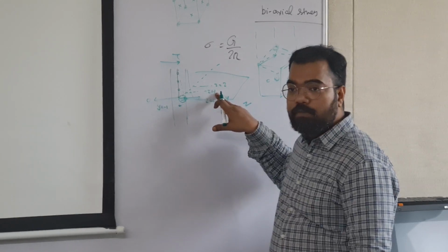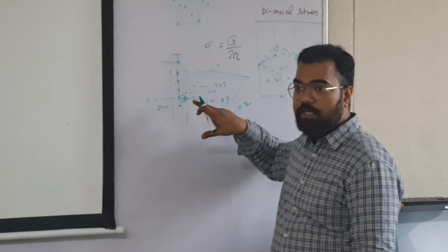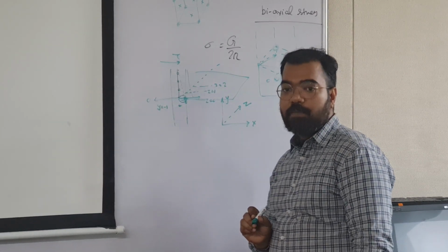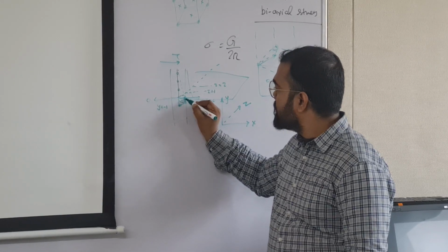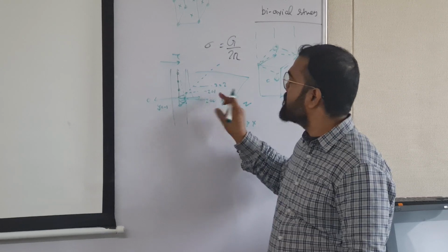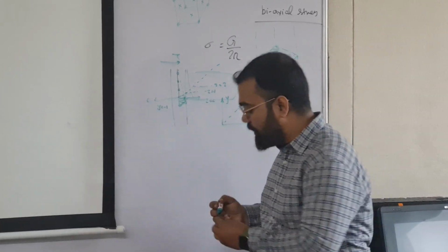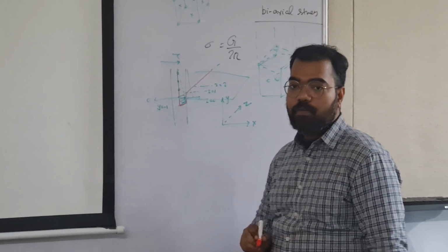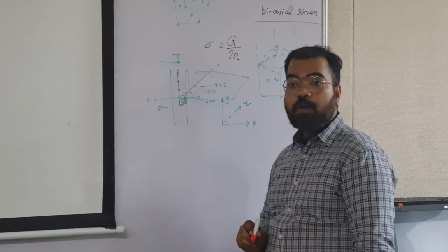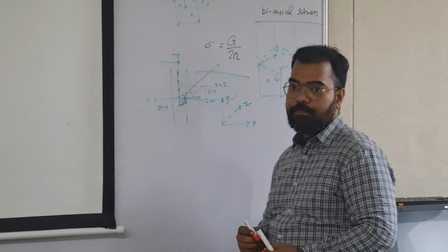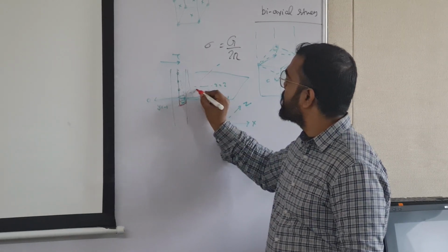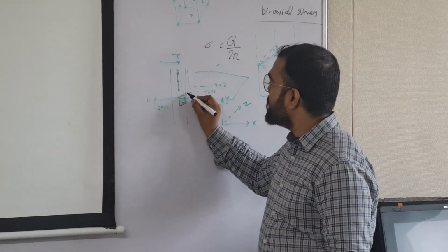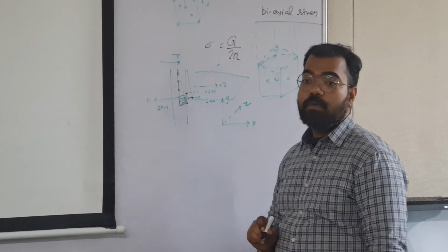But what happens to z is equal to 1? It is not there. It is at y is equal to 0, right? So I could put one atom there also, but then I don't put any other atom. Then what happens? The dislocation extra half plane definition is this for z is equal to 0 and z is equal to 1. And beyond that, now if I want to draw the dislocation line, then that dislocation line will look like this. Right? Now tell me how this thing will move. As long as it was just like that, it could move. Right? But in order to move for this assembly, this part also needs to move, although that is not on the plane.